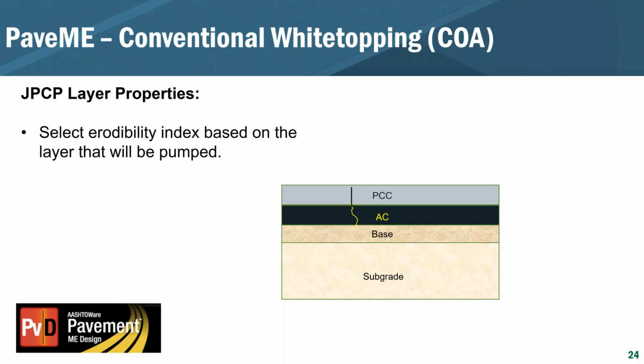The first thing you come to when you're doing your design is the layer properties for your overlay. The big thing with this is selecting the erodibility index based on the layer that will be pumped. It's important to remember that the material being pumped for a white topping is pretty much always the material below the asphalt layer. If you just assume it's directly the layer below the concrete, that's not quite true with a concrete overlay over asphalt, because as those joints open up, the crack propagates down through the concrete and through the asphalt as well. So that joint activates typically through the concrete and the asphalt layer.